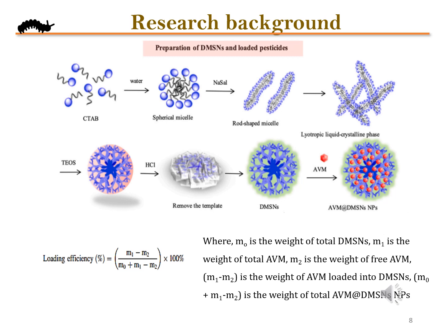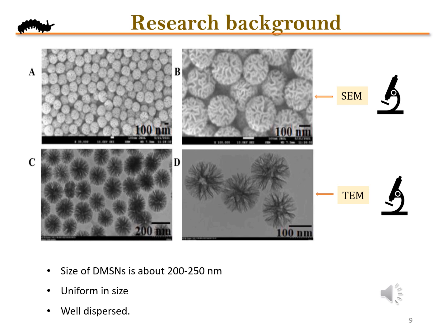The drug was loaded onto the silica nanoparticles by making a concentrated saturated solution of AVM in methanol and mixing nanoparticles into it. The drug loading efficiency was calculated using the formula shown here: (M1 minus M2) divided by (M0 plus M1 minus M2), multiplied by 100. The synthesized material was characterized by different characterization techniques like SEM analysis, and the results are interpreted below.